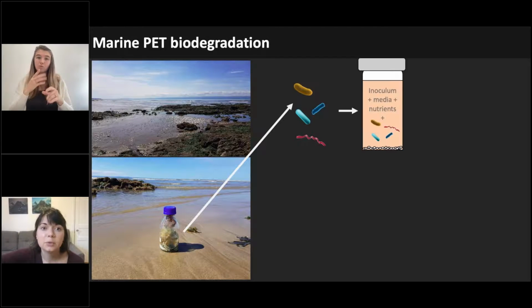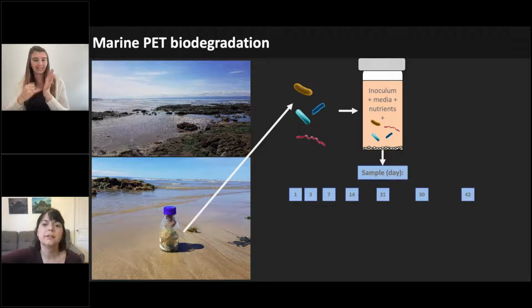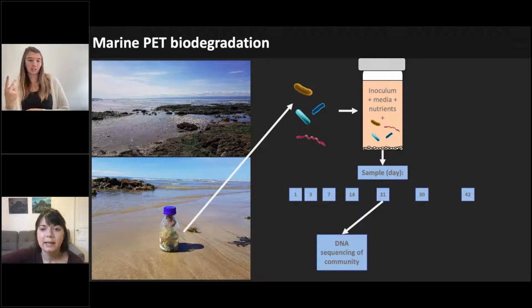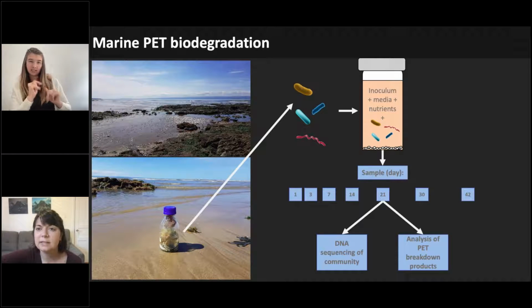First of all, I added them to water, nutrients, and one of a few different types of PET, and I examined how this community of microbes changed across 6 weeks of incubation, taking samples on days 1, 3, 7, 14, 21, 30, and 42. And I used these samples to both sequence the microbial community and to look for breakdown products of PET in the surrounding water.